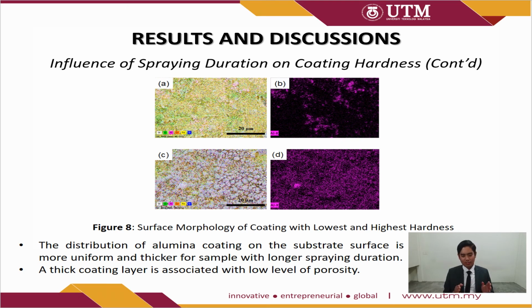Basically, figure 8 indicates the surface morphology of coating, with figure 8A and 8B indicating the surface morphology of coating with lowest hardness, while figure 8C and 8D show the surface morphology of coating with the highest hardness. As we can see, the distribution of alumina coating on the substrate surface is more uniform and thicker for sample with longer spraying duration. This occurs as the majority of flight particles are semi or fully melted in the plasma jet before being impacted on the substrate, forming a dense coating structure and enhancing the flow and compaction of coating during the build-up process. Besides, the value of Vickers hardness increases as well due to effective flattening and solidification of the powder particles over the deposited layers.